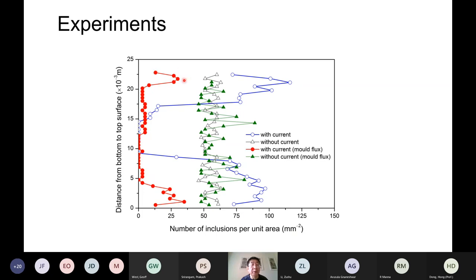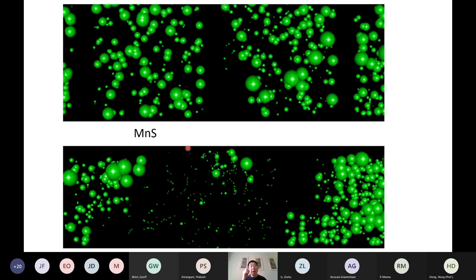So in the solidified metal, the inclusions are extremely low. Here is an SEM image. We did this SEM image and we used that visualization software to plot it, because without it you can't see. The reason is the scale: the metric scale is in centimeters, but each particle is only a few micrometers. So you won't be able to see it. If you plot that using the SEM machine, it's just a point you can't see. So we can use a two-scale plot here.